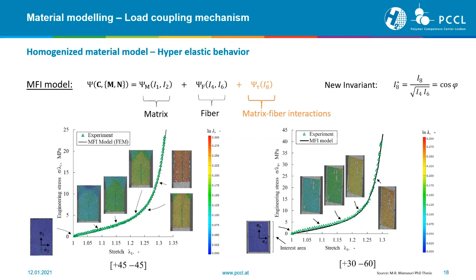And here you see two examples, one for plus minus 45 and one for plus 30 minus 60. As you see in those two results, the experiment, indicated by the green dots, fits the MFI model that we've developed here very well, for this plus minus 45 as well as plus 30 minus 60. Additionally, you see also the surface strain, which we directly measured with the camera system for these two setups.